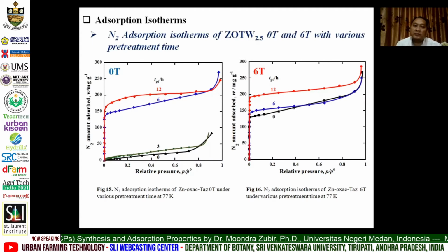So to investigate the pore properties of these PCPs, we observe by nitrogen adsorption isotherms for 0 Tesla and 6 Tesla. And this is the pretreatment temperature before the adsorption. So we measure without the pretreatment temperature, and also with 3 hours, 6 hours, and 12 hours pretreatment time. And for 0 Tesla, with no pretreatment and only 3 hours of pretreatment, the pore is not yet formed. If compared with 6 Tesla, without the pretreatment temperature and also 6 hours and 12 hours, the pore is already formed for this magnetic field crystal.